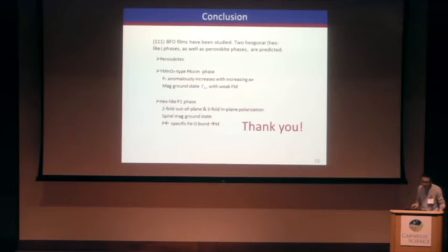To conclude, we focus on the 111 BFO films, and besides the perovskite, we found two hexagonal or hexagonal-like phases. They have quite novel magnetic and electrical properties. Thank you.